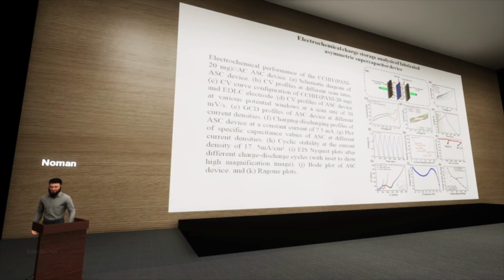Similarly, the device was further investigated after each 5,000 cycles to find out the effect of impedance on the device performance. And this is the Bode plot, which is also showing the similar effect of the impedance. And this is the famous Ragone plot, which is showing that our device is showing very good energy density and power density with respect to previously reported similar materials.